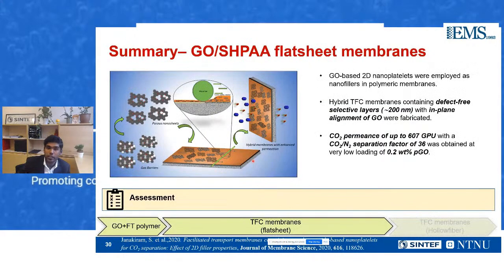So in conclusion about this study, 2D materials are very good as nanofillers to be dispersed in facilitated transport membranes. Given the extremely thin nature of graphene oxide in one dimension, we got defect-free selective layers of less than 200 nanometers, and in-plane alignment of GO, in these hybrid facilitated transport membranes cast as thin film composite.